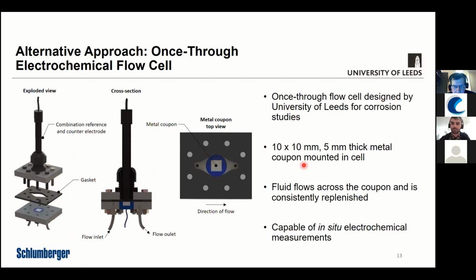And we get some very precise electrochemical measurements because we've got an ideal environment for that by placing the electrodes very close together. Just to give you an idea of the size of this, this is all to scale. This coupon is 10 mm by 10 mm. So the whole device is fairly small, which is convenient for lab experiments. Flow loop or pipe flow experiments are much more difficult to fit into a laboratory environment, and not as controllable. This is a very convenient way of doing controlled experiments, and it essentially overcomes a lot of the challenges faced by doing these experiments using a rotating cylinder electrode or static glass beaker tests.